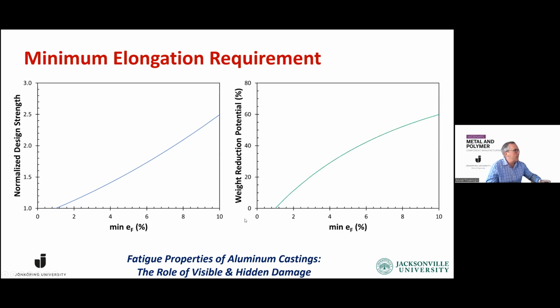So what does that mean? The weight reduction potential goes up. When the design strength goes up, the part can be smaller, so the weight reduction potential goes up. This is only in percentage. It can go up to 60% if we increase our minimum elongation requirement from 1 to 10.